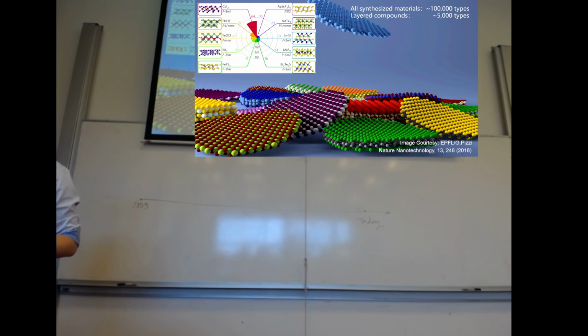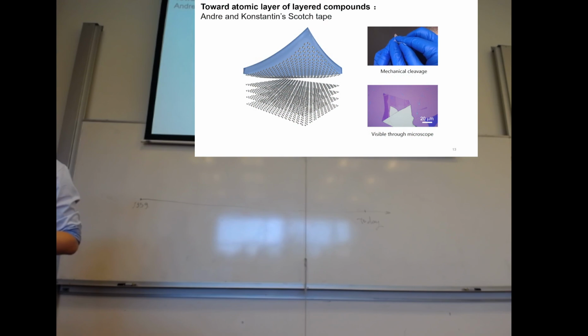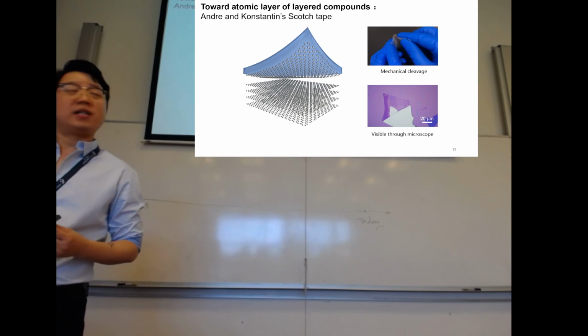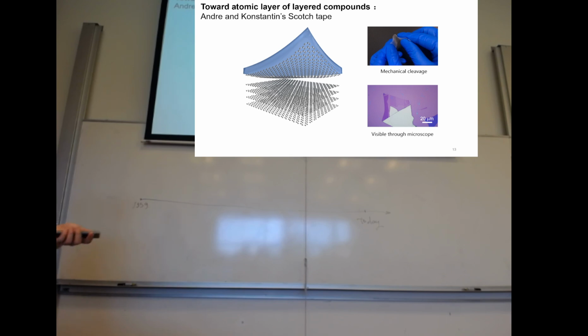But why did nobody at that time start exfoliating them? Because you need something which is really magic. You need to see that thing, and you have to have a good method to exfoliate. So the first experiment was done really easily. If we look into that story now, it looks even ridiculously simple. You just take a scotch tape from any shop, any supermarket. Then you exfoliate some kind of graphite. Of course, it has to be a layered, single crystal or crystallized structure. Then you just fold them several times. You press on a silicon oxide wafer, and under the microscope, you will see a very thin film.